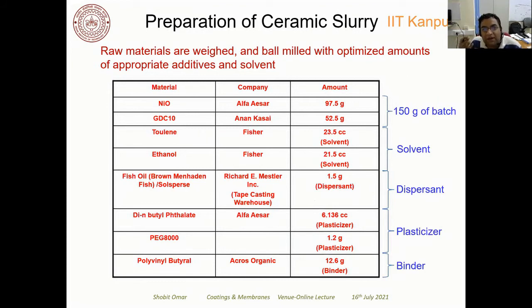So this is one of the recipes of a ceramic slurry that I have stated. What we are trying to do is make a tape of a composite material based on nickel oxide and GDC, and if you have to make such a tape, you require a large batch of material. Normally we use a 150 gram batch, and then you add some solvents which are volatile in nature. Toluene and ethanol we normally prefer, and then we also add some dispersant so that these particles are well dispersed inside the solvent. We add plasticizer, which is made of DBP and PEG.